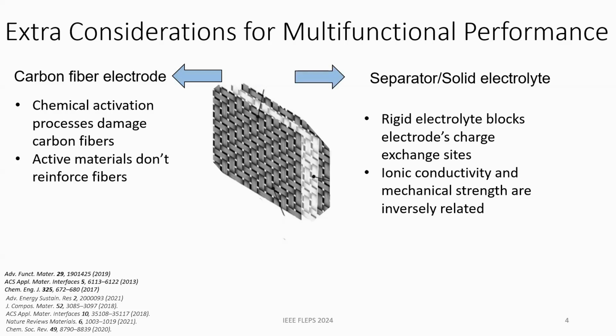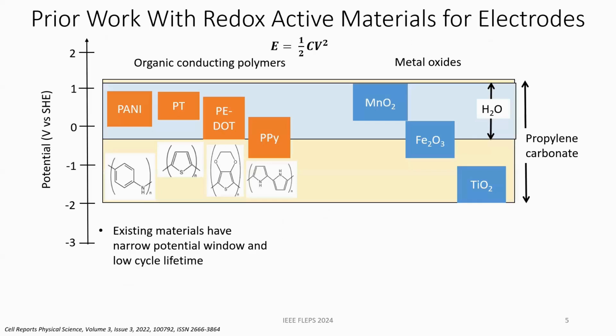The next consideration is our solid state electrolyte. Going from a monofunctional liquid electrolyte, we need to have structural strength, so it needs to be more rigid, but then the rigid electrolyte can end up blocking the charge exchange sites. And from that point, if we try to improve the ionic conductivity, it can greatly reduce the mechanical strength. So the key to make this work is to have a good electrode-electrolyte interface. I'll be talking about first our structural electrodes, electrolyte, and then our full device.